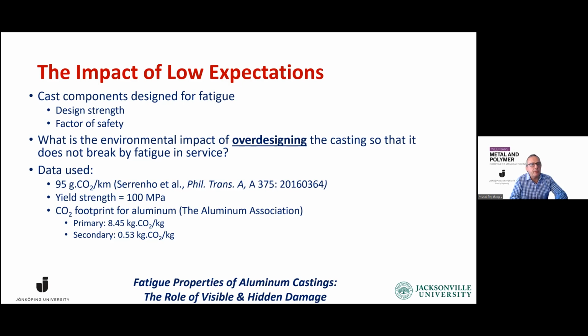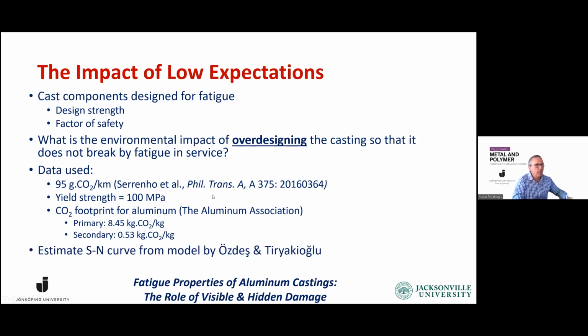The carbon footprint for aluminum, the latest numbers I found from the Aluminum Association, is that primary aluminum has 8.45 kilograms of carbon dioxide per kilogram of aluminum, and secondary aluminum has half a kilo of carbon dioxide per kilogram of aluminum. So we're going to estimate the SN curves from this simple model that we developed, and we're going to apply it to this thought experiment.